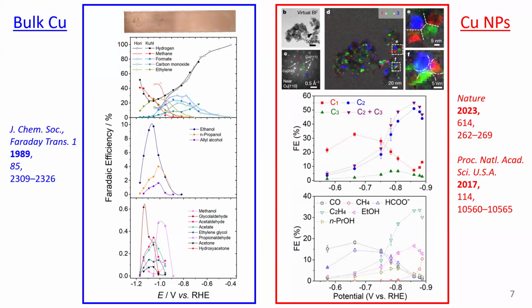And if we look at the initial work versus the state of the art today, what has changed? Well, instead of using a bulk slab of copper, now we're using nanoparticles, and that allows us to create unique structures that improve the activity. Specifically, in electrochemistry, your potential is a measure of your driving force. So if we are able to reduce CO2 at a lower driving force, that's a more active catalyst. So we can improve the activity slightly, and we can improve the Faradaic efficiency.